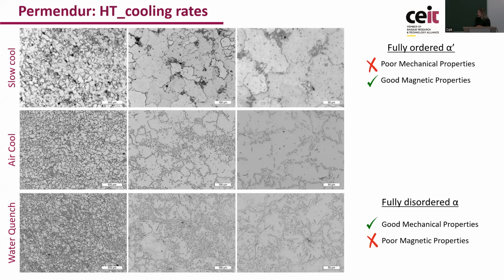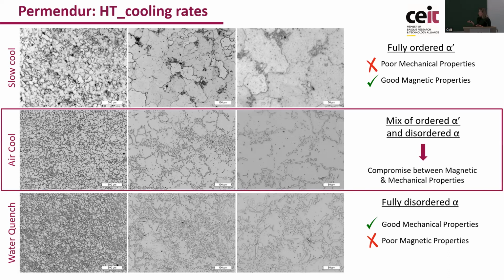In the case of the water quench cooling rate, again, we observe a lot of small grains that are related with alpha grains. And again, as in the material coming from the AM, we have good mechanical properties, but again, the magnetic properties were low. So it's clear that if we increase one property, the other one decreases. So finally, what we saw is that we have to achieve a compromise where we have an intermediate cooling rate that is giving us a microstructure with a mixed alpha prime phase and alpha phase.